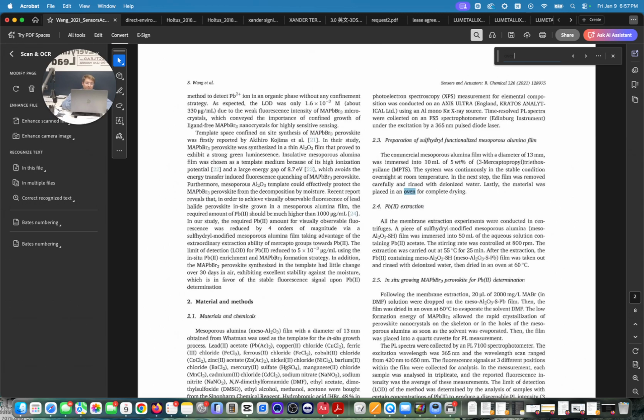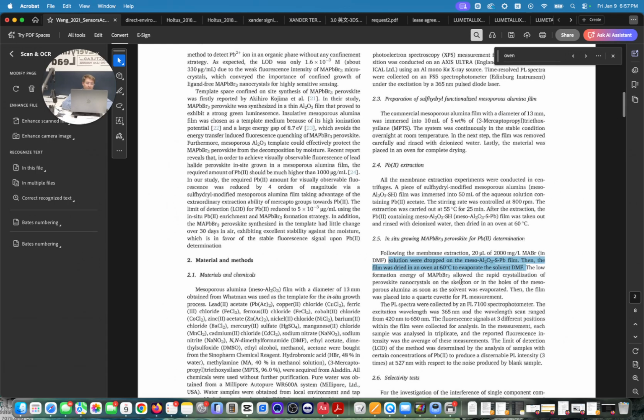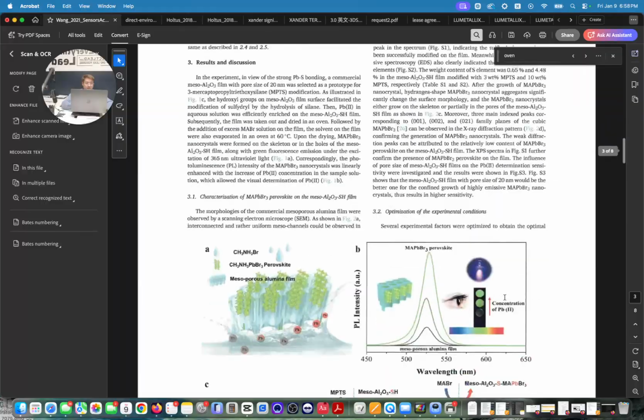However, it's not immediate. In this circumstance, the methylammonium bromide did not show itself until there was an evaporation. So you can see they used an oven here at 60 degrees Celsius to evaporate the solution, and you see that they dripped it onto the surface. And so once they dripped it, they could see that the low formation energy of methylammonium lead bromide allowed the rapid crystallization of perovskite nanocrystals on the skeleton or in the holes of the mesoporous alumina as soon as the solvent was evaporated. Then the film was placed in a quartz cuvette for photoluminescent measurement. But they could see it with their very own eyes, and you can see that by the photos here.